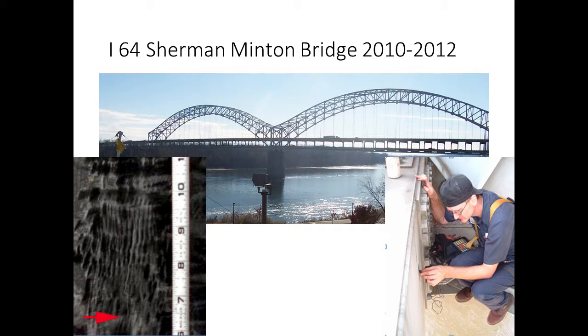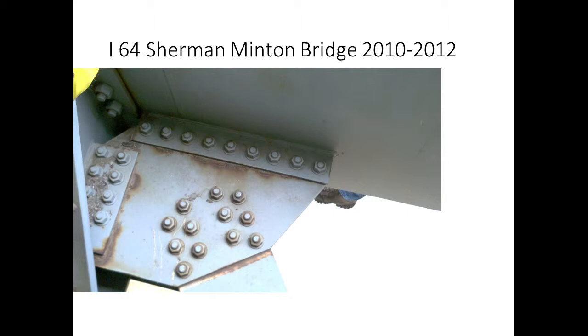As time went along, the Indiana DOT had some additional concerns, and they determined they were going to perform non-destructive testing and evaluation of the box girders for that problem and other issues. And here you can see a technician doing some inspection on one of these transition butt welds. This is a particular area that was being retrofit during the inspection process. What you have here is a shelf plate, and it's welded onto the inboard web of the tie chord, and you can see that it lapped over the top of this transition butt weld. They were cutting these out, and then they were replacing them with a bolted attachment.